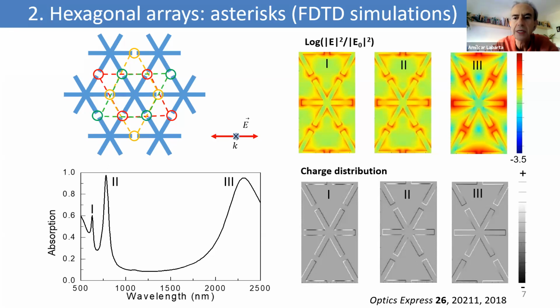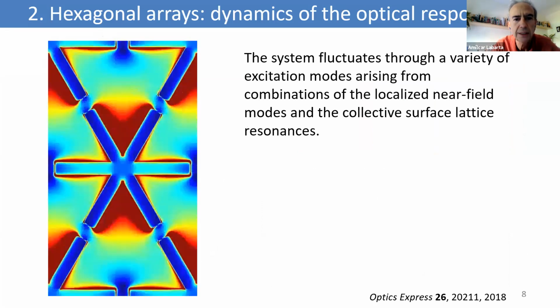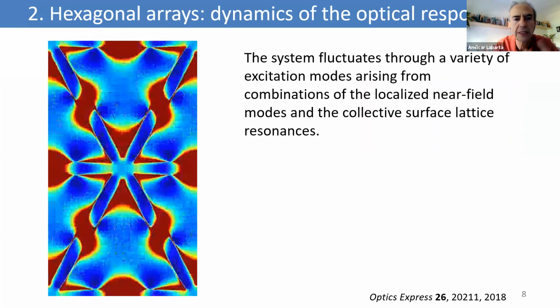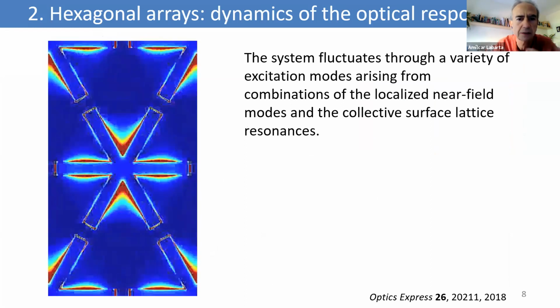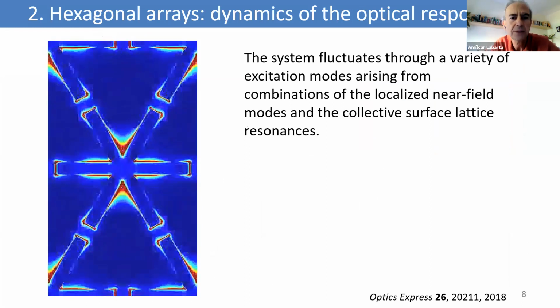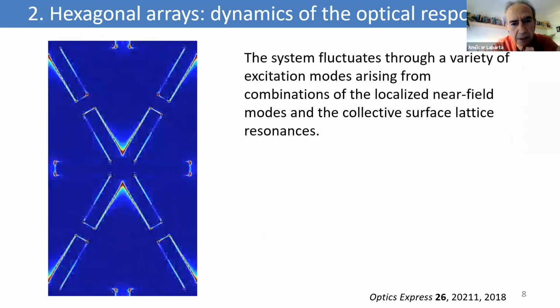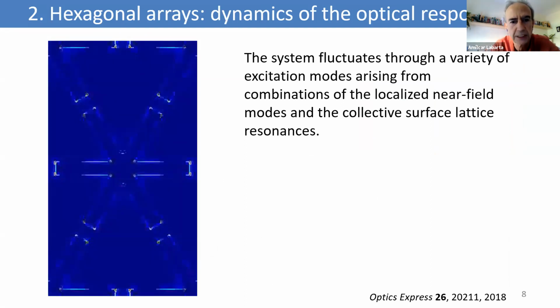And you are going to see in the movie that I am going to show you that the system fluctuates between near field interactions, which are characterized by the shining of the gaps only, and collective modes that correspond to the shining of more or less the whole surface. So here the movie, you see that the system fluctuates in a complex way between these two kinds of excitation. And there are certain times at which the full surface of the system shines.